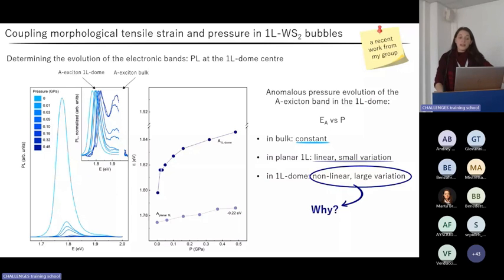Regarding the photoluminescence spectrum, we notice again a dramatic decrease in the intensity of the monolayer signal as a function of pressure, which can be related to the decrease in the bubble height. However, what is most interesting to notice is the evolution of the A exciton energy as a function of pressure. As you can see from the figure reported over here, in the case of a planar, unstrained standard monolayer, the pressure evolution of the A exciton energy follows a slowly increasing trend with an almost constant rate. Conversely, in the case of the monolayer dome, the variation in energy of the A exciton band is much larger and mostly highly nonlinear.